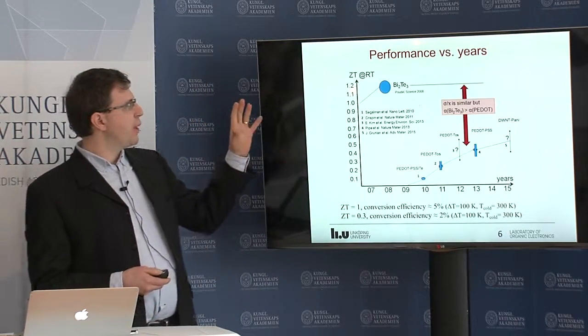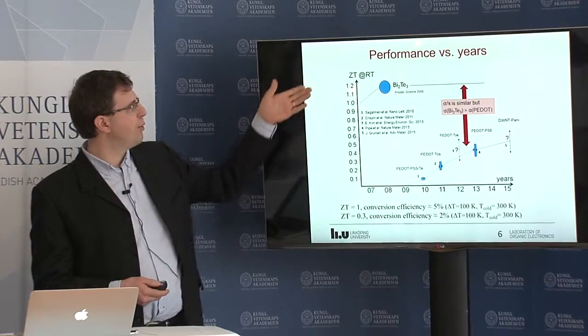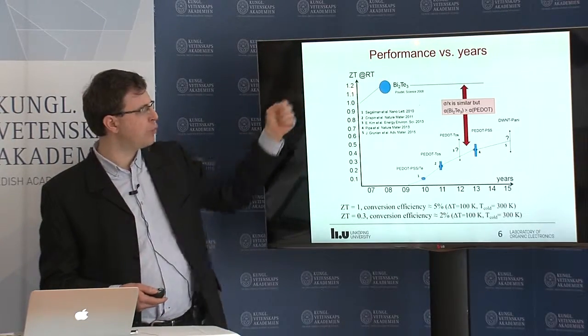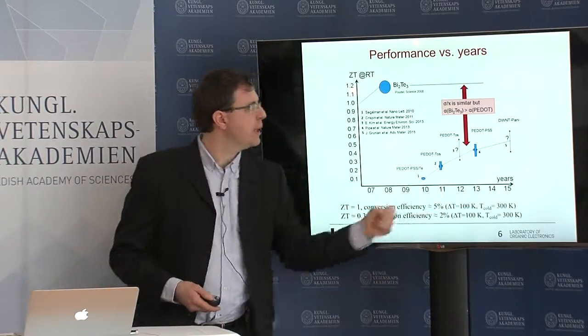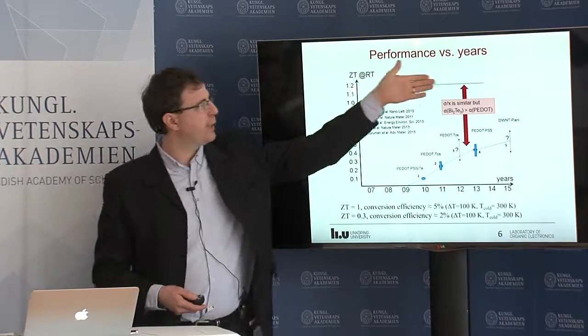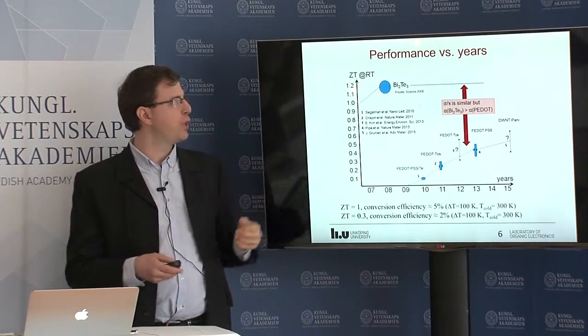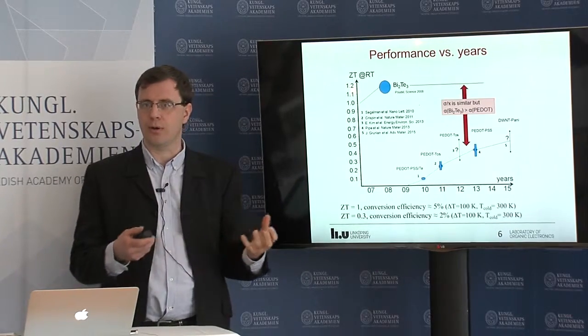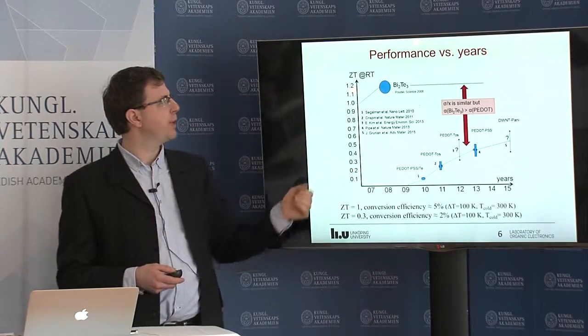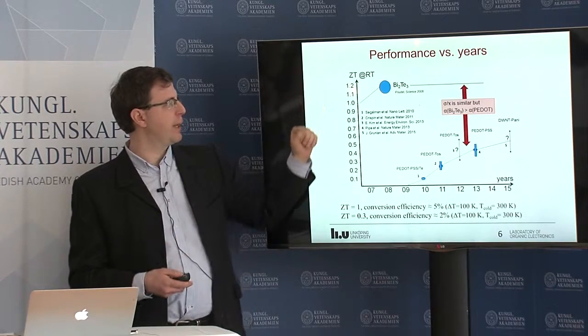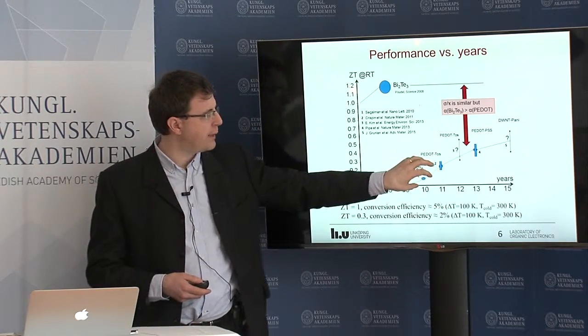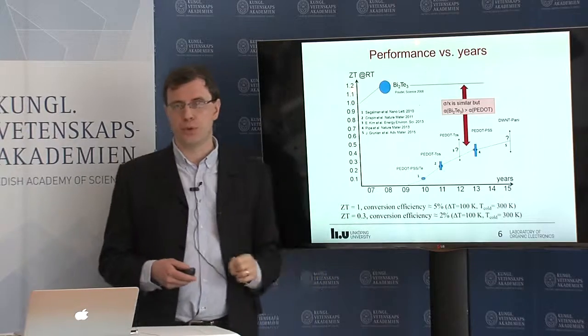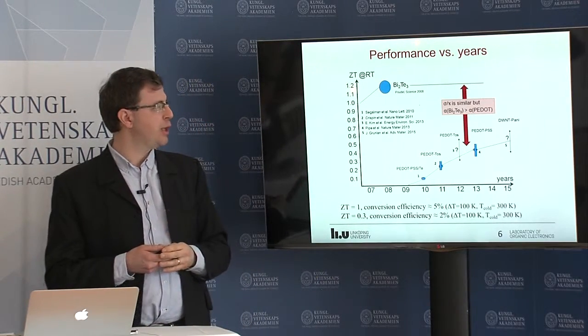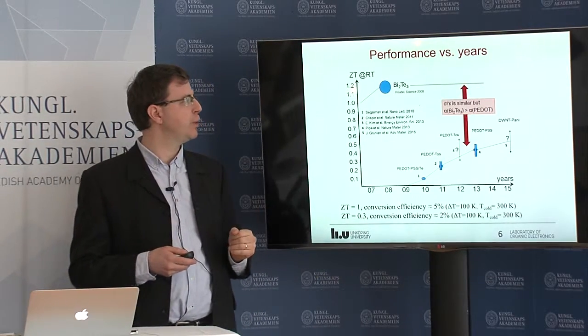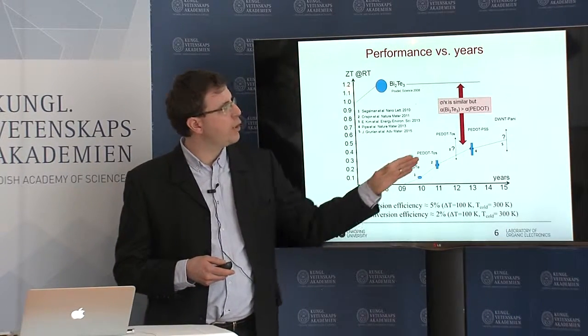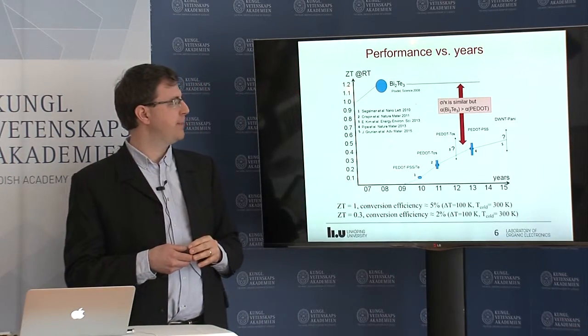So here is a graph where I report the value of ZT at room temperature versus the years, and compare with the inorganic one, which is the state of the art, bismuth telluride. You see, tellurium is an atom that is not very abundant. It's quite an efficient material. And here, after our findings, there have been other research steps achieved by different research groups in the world, showing an increase of the ZT value, basically.